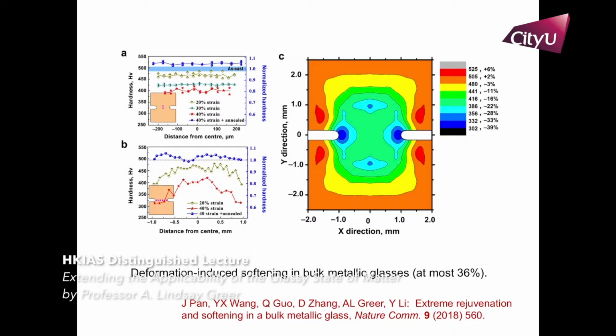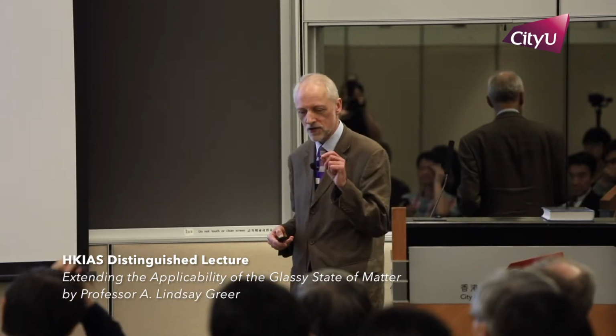It's a bulk metallic glass, a few millimeters across, and this color map is a map of hardness. And it's showing that far enough away from the action of the notch, you have the original hardness of the glass. But as you go into these central zones, you move along this color scale, and you actually move to regions of significantly lower hardness. In fact, it's lowered by as much as 36% at these points. That hardness change is presumably telling us something about a structural change, and the other way we can characterize that structural change is in terms of energy.